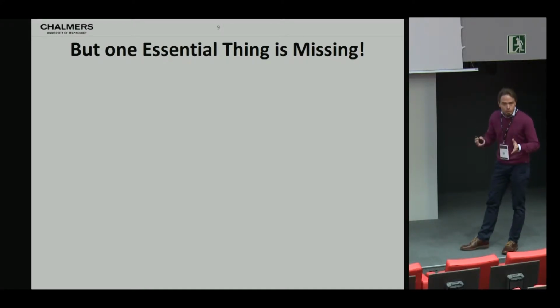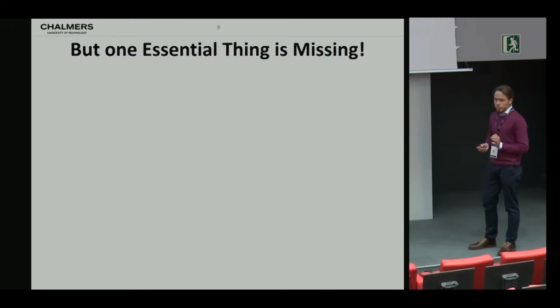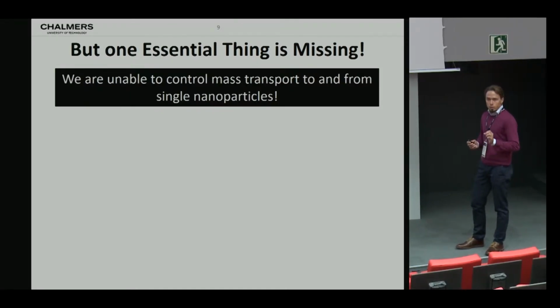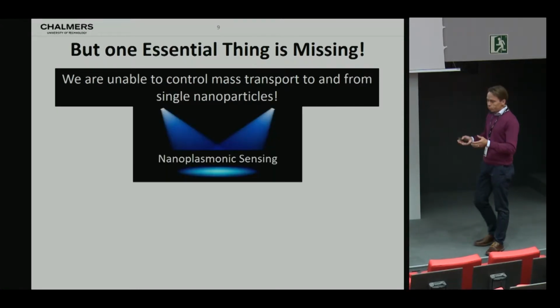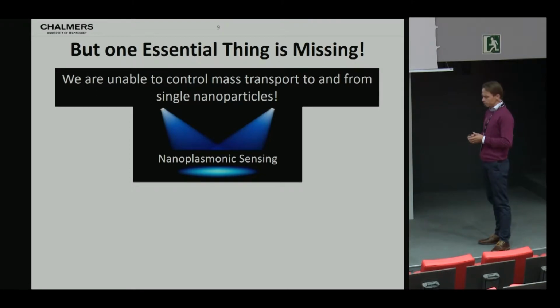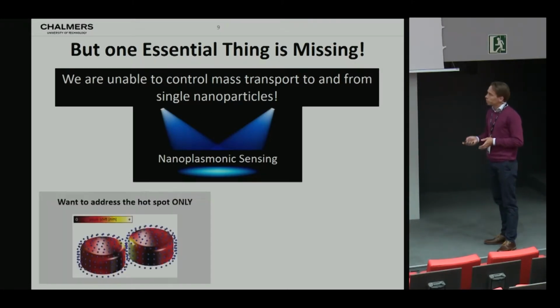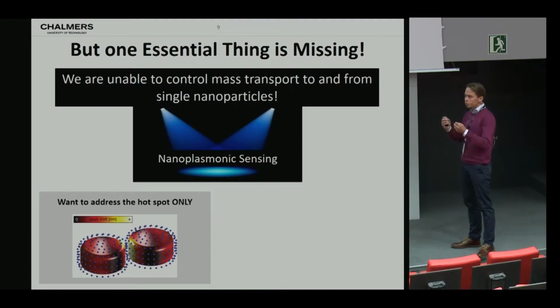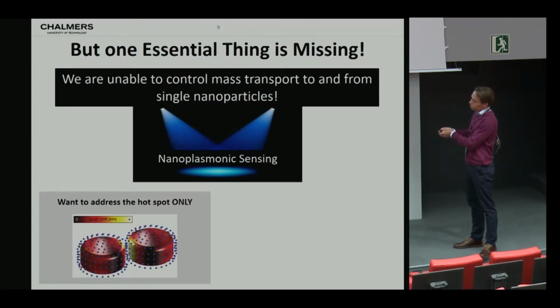Let's be fair, there are many experimental methods to do that, electron microscopy and X-ray diffraction techniques that can do that, but I believe there is still one essential thing missing in this context. And that is, we are not able to control the mass transport of molecules to and from single nanoparticles while we are studying them. And if we project this statement onto nanoplasmonic sensing, there are a number of reasons why this would be very desirable. The first one, as you all know, is that if you use a plasmonic antenna as a sensor, it is not uniformly sensitive. Essentially, as shown here by these blue dots, if you bind a molecule to these positions, it's only here in the hotspot where you actually generate a signal.